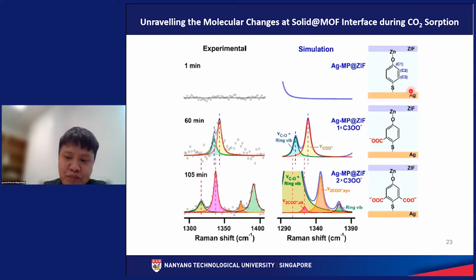So we have a range of products that we hypothesize. Okay, so they involve ortho-carboxylated product or meta-carboxylated product. So is it 1 or 2 carboxylation reactions? So we try a series of various combinations and we exclude the others and only isolate these 3 species out. If we compare the experimental and the simulation data, we can see that the SERS spectrum at time equal to 60 minutes corresponds to this molecular configuration over here. So there is a carboxylation occurring at the meta position. So again, this is ortho meta. Okay, so this tells us that there is 1 carboxylation reaction at the meta position.